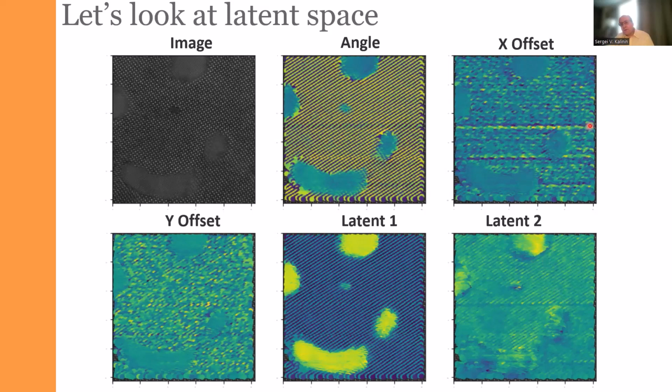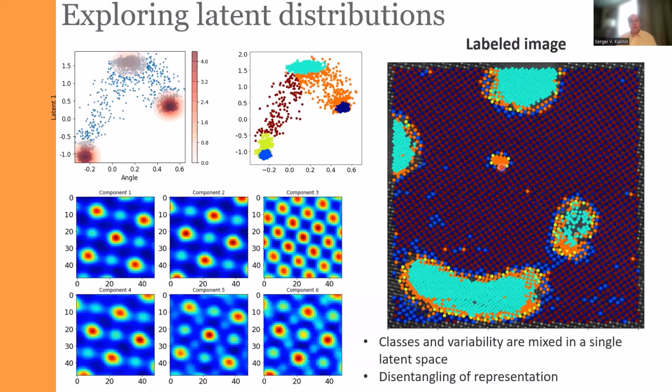We also see that, interestingly, one of our channels starts to have this horizontal line. For those of you who are familiar with microscopy, this is obviously the non-ideality of the scanning system. And if we can separate it, then we can correct for it. We just make this offset 0, and then we use the generative property of the autoencoder to reconstruct the object without the shear. So we can play more with it.